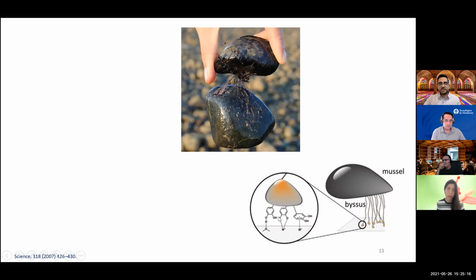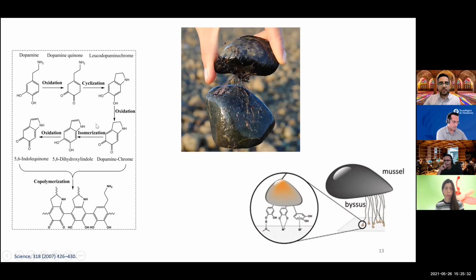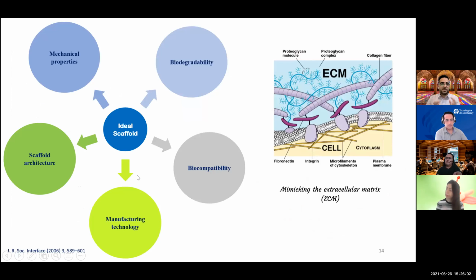Recently, dopamine, a small monomer, has been introduced as a monomer that can mimic the structure of this interface, because dopamine contains both amine groups and phenolic groups. Under basic conditions at high pH, we can trigger the polymerization of this monomer, and after oxidation, cyclization, and isomerization, we will have a thin copolymer that can attach to all surfaces. Okay, it's the first concept.